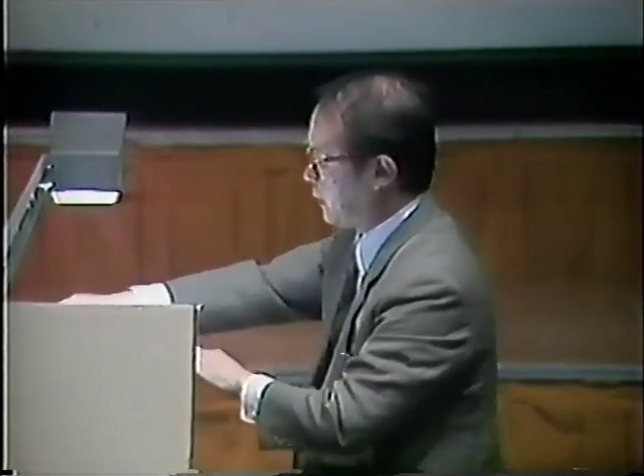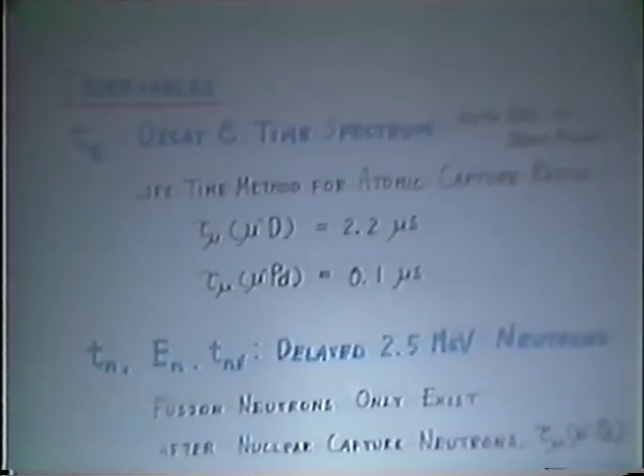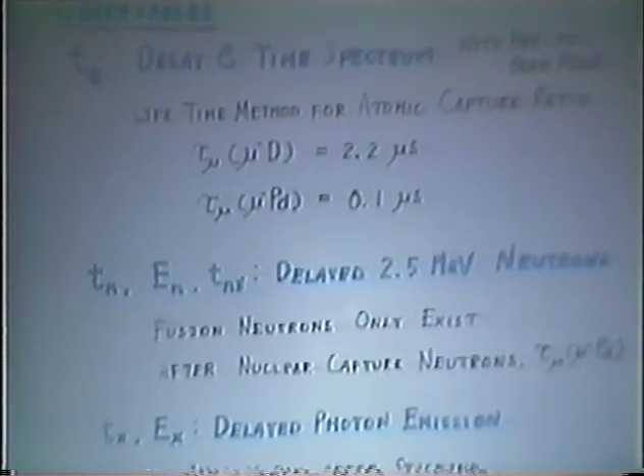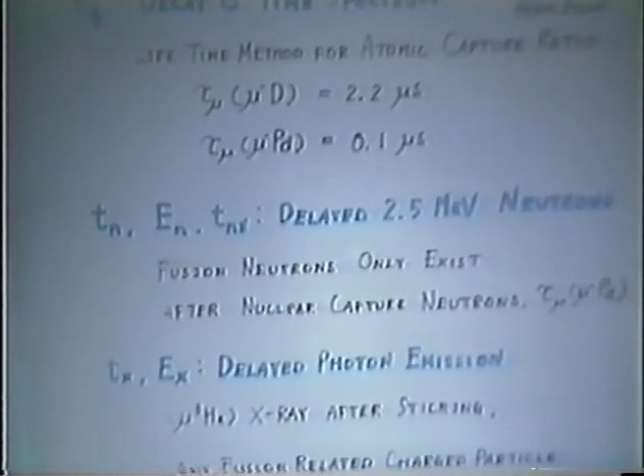So let us come back to condensed matter fusion. The observables in our experiment are summarized here. First of all, the decay electron time spectrum with reference to the beam pulse, which is useful for the so-called lifetime method for the atomic capture ratio determination. When the muon is captured to deuterium, the decay time constant becomes 2.2 microseconds, while when it is captured to palladium, it becomes 100 nanoseconds.